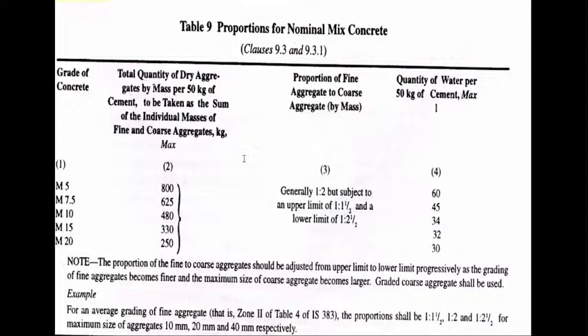Now you have taken 50 kg of cement, take 250 kg of total aggregate. But if you read further, it says it is generally 1:2, but subject to an upper limit of 1:1.5, which means this 1:1.5 is having slightly lesser coarse aggregate, and a lower limit of 1:2.5. This 1:2.5 means it has got more coarse aggregate. Now we will dwell upon this after we look at the next column.